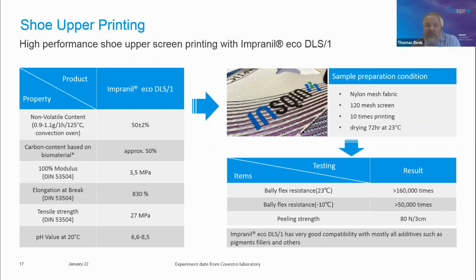It is a medium soft dispersion with a very good elongation and a good tensile strength of 27 megapascals, as well as a high elongation of more than 800%. Impranil Eco DLS/1 has very good compatibility with mostly all additives such as pigments, fillers, and others.